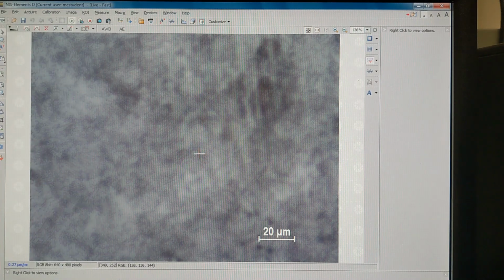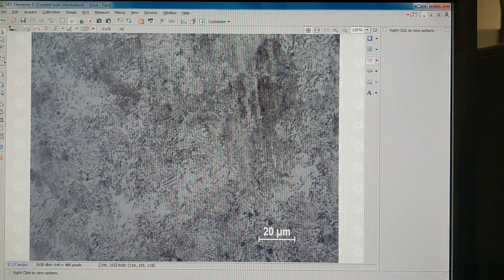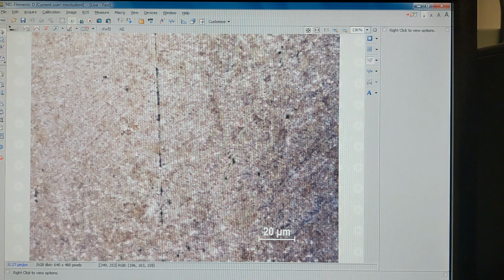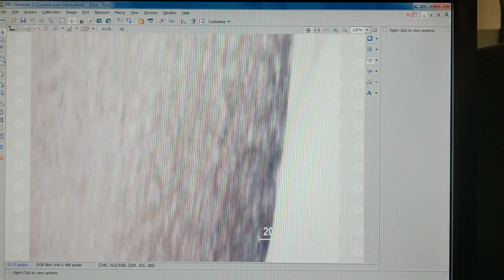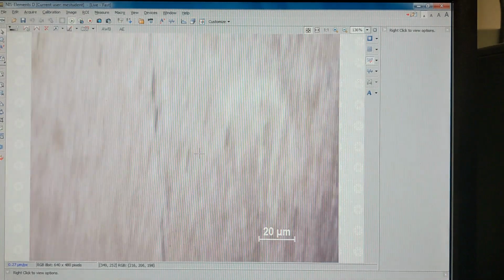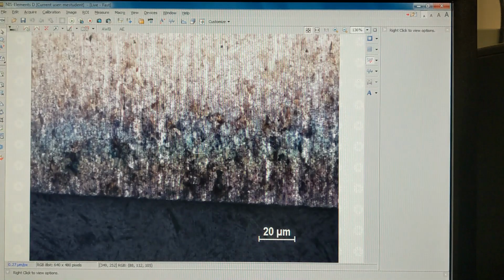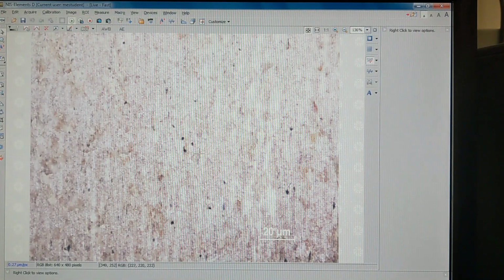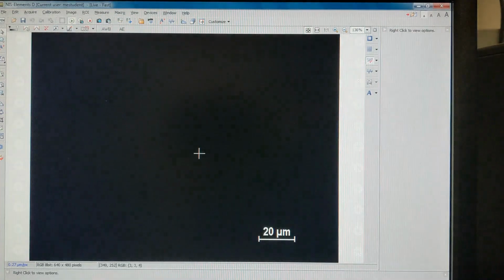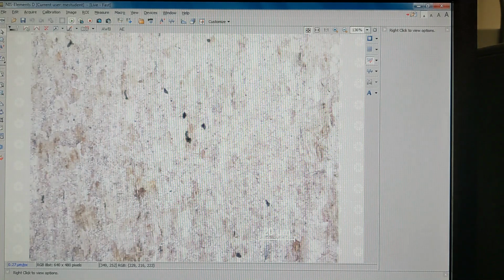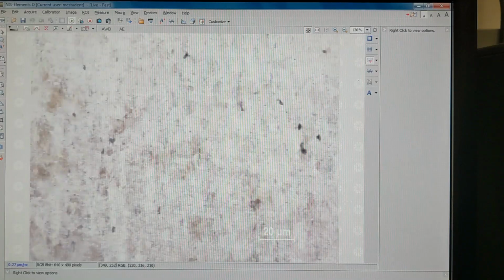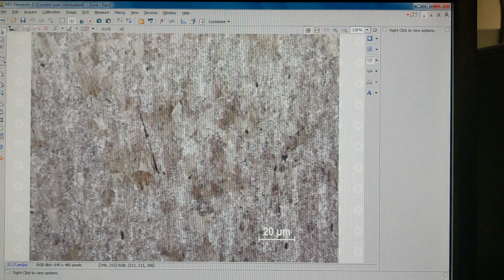And this is our cold drawn sample. So this is actually our circular cross section. Now if we go to our flat cross section, which should run parallel to the direction of drawing, we'll go back to 5 times. And if we find our other sample, it's not there, let's go the other way. Here it is. So we find our other sample. Let's zoom in. Let's adjust the brightness a little bit. You can hopefully see lightly we have an orientation that is going downward in this direction.